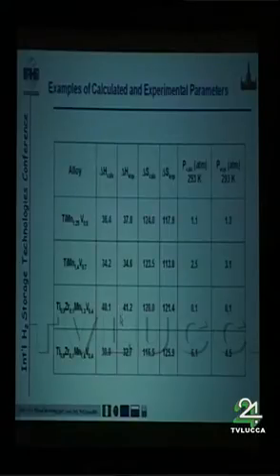Actually, we can see that our model and our equations give rather good results, and here we can see the comparison of calculated and experimental values for enthalpy, entropy of reaction, and even for equilibrium desorption pressure for some alloys of ternary and quaternary systems. And we see that we have very good correlation of calculated and experimental values.